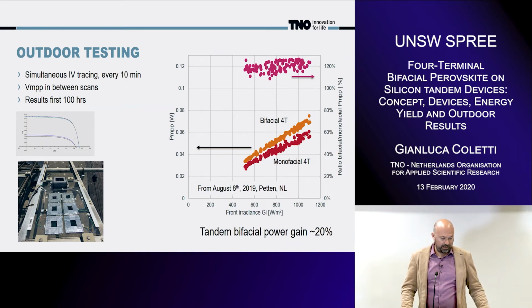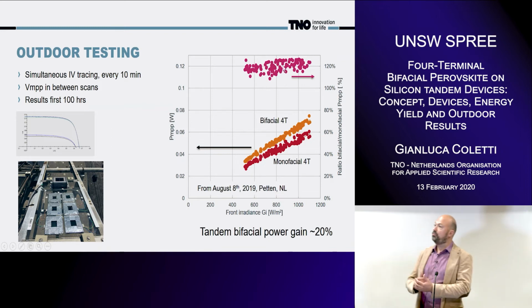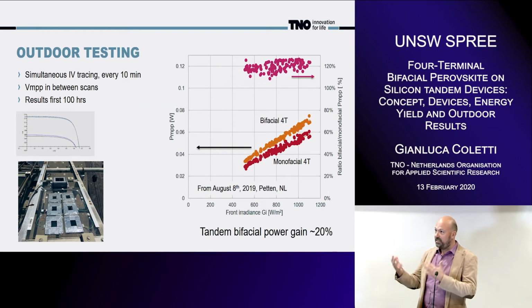of light, and here we plot the power of each module as a function of the front irradiance. You see here the bifacial four-terminal as a function of the monofacial four-terminal, and the ratio between these two is approximately 20%, which is what we have seen in the calculation, where you have roughly a gain of 20% in the energy generated. That's what gives this equivalent efficiency boost of 20%.